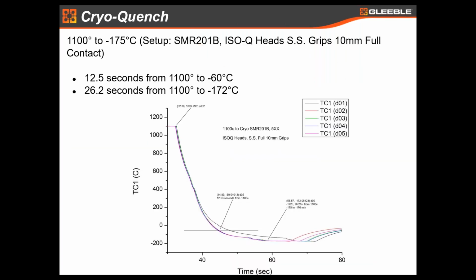Here's some data. In this test, we went from 1100 C down to -175. Again, you can see some of the setup information for our Gleeble users. That makes sense. You can see the specimen type. Again, we use the ISO-Q method, stainless steel grips. It was a 10 millimeter full contact specimen.